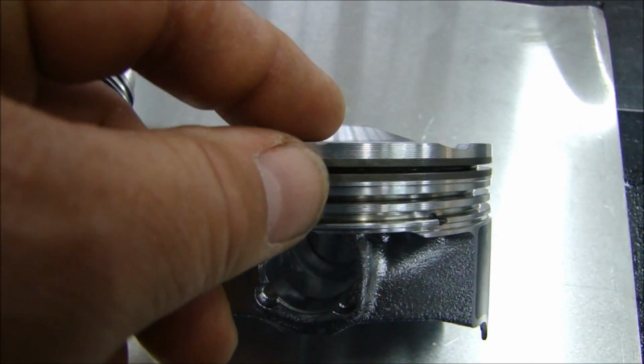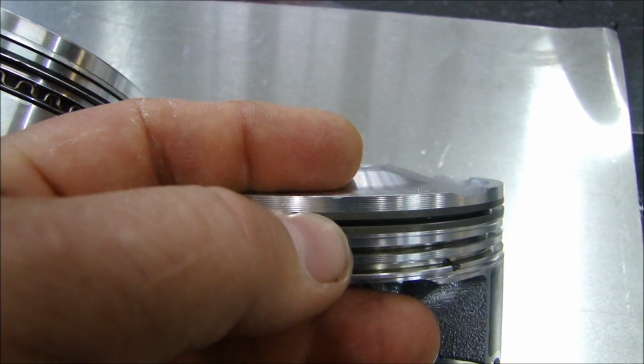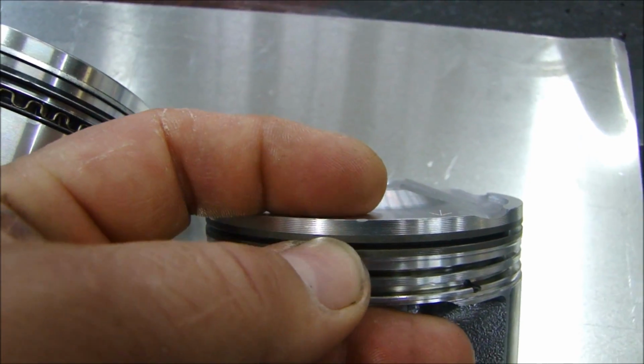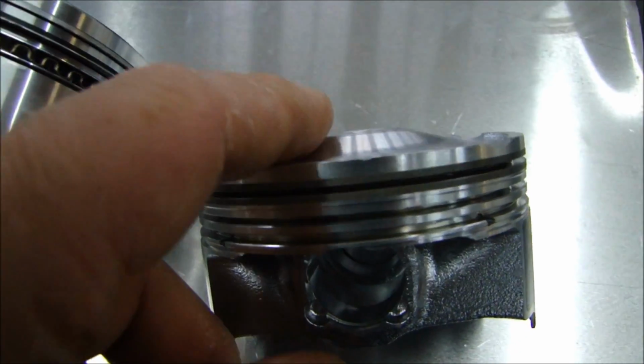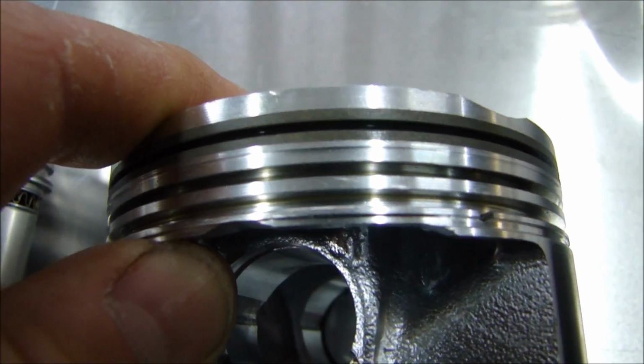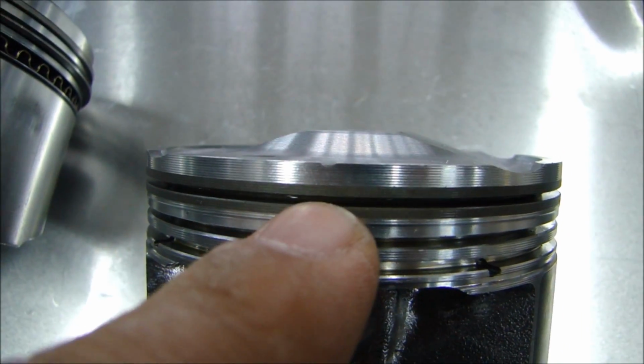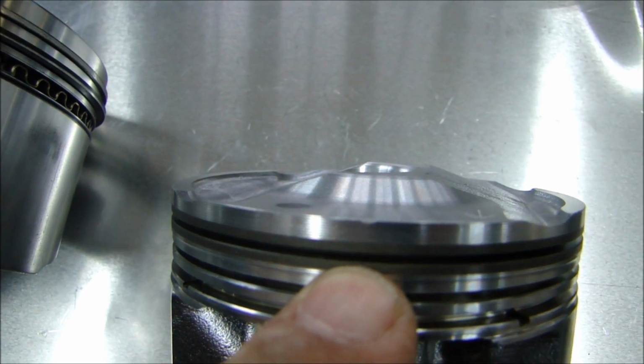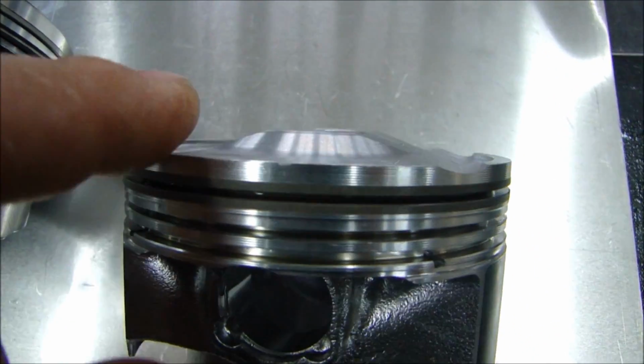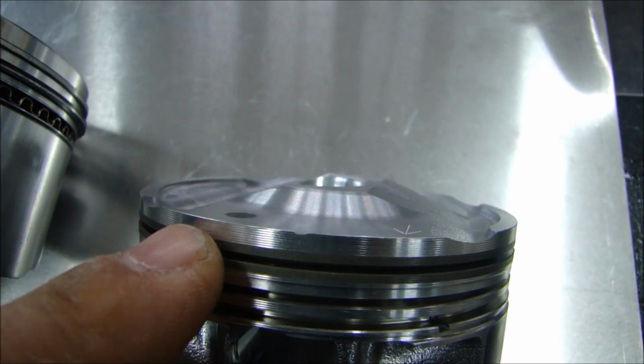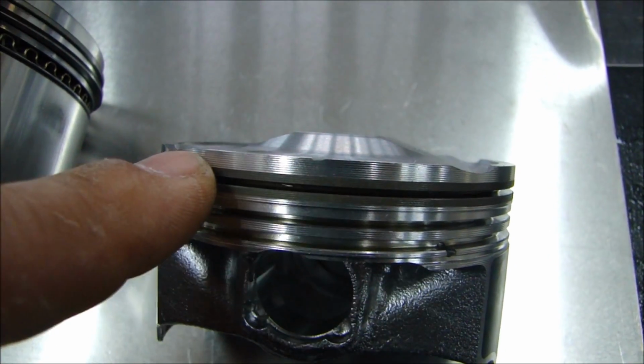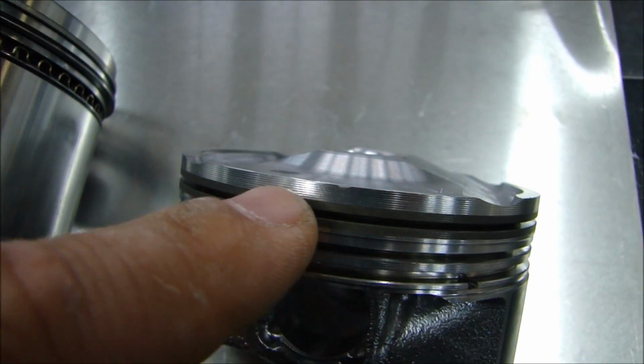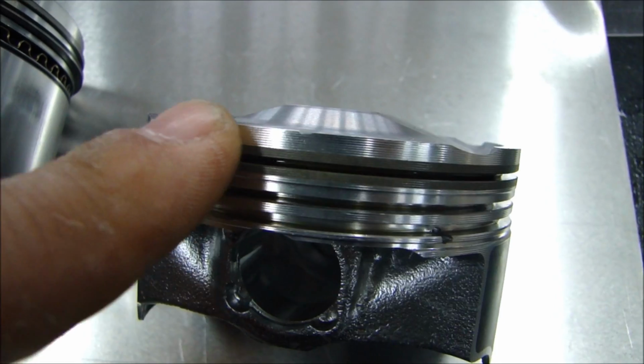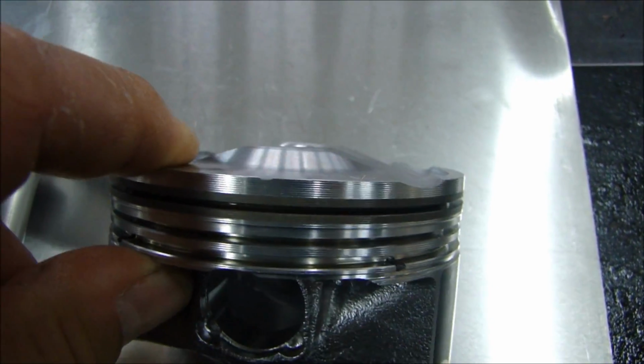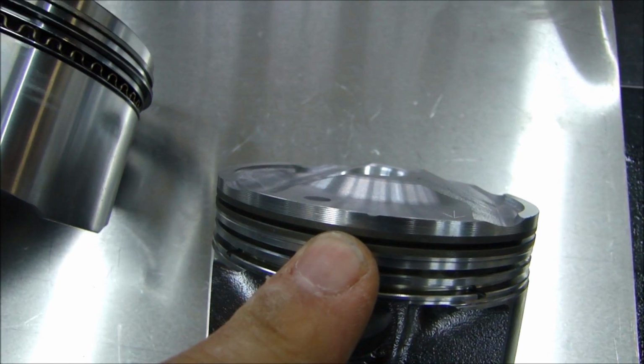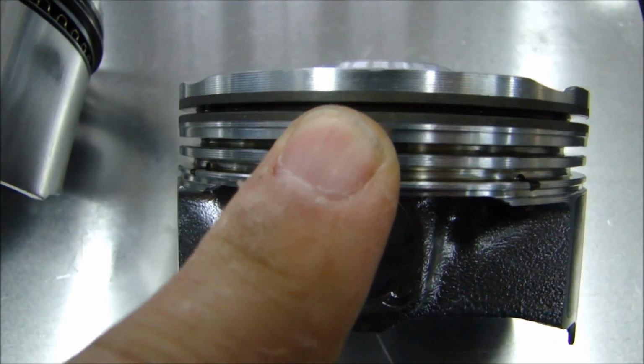But when we make this here, we get increased risk of cracking for the land failure here. This land can crack, and what they do to try and help that is, if you can see very closely, that top ring, this top groove here, is anodized. And it's anodized very simply by putting sulfuric acid on aluminum, in a very controlled fashion. The sulfuric acid produces an aluminum oxide coating in that ring. And that aluminum oxide coating makes that groove much harder, more durable, and less prone to the groove distortion and micro welding that can occur when you get high temperatures on the dome.